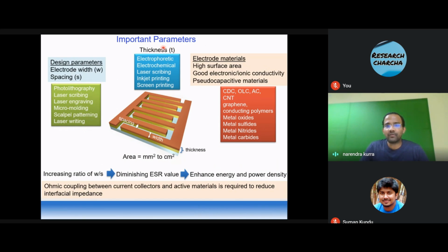And coming to the loading of active material, that is called thickness. So here the typical deposition techniques include electrophoretic deposition and electrochemical deposition methods. Laser scribing is a conversion technique, it's not a deposition technique. Inkjet printing and screen printing are the routinely used printing techniques for deposition of active materials. In terms of electrode materials, there are two main classes. Those include carbon materials, whose mechanism is based on adsorption and desorption of charges like ions, formation of electrical double layers, and also pseudocapacitive materials including metal oxides, sulfides, nitrides, and carbides.